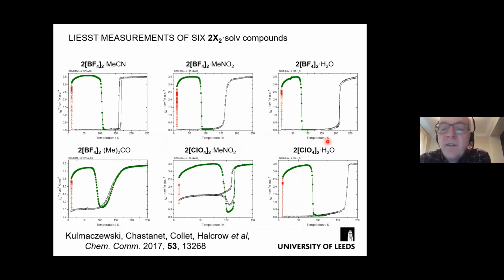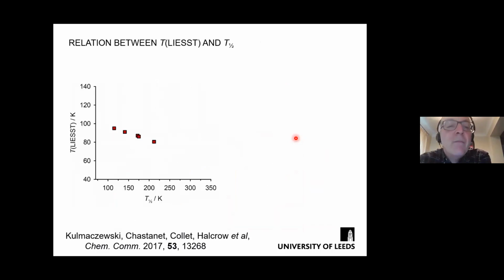Now, I said we would look at the photomagnetism. This is data from 6 of the compounds showing that they give good LIESST measurements. And if we do this same graph, plot T(LIESST) versus T half, again, kinetic versus thermodynamic spin transition, we have a perfect straight line for 5 of the compounds. But the 6th compound goes here. And we didn't understand that at all for a long time.